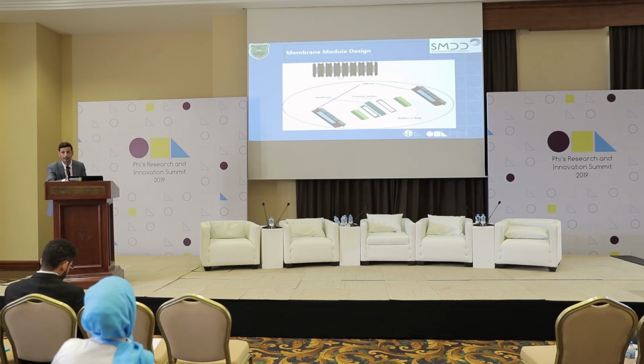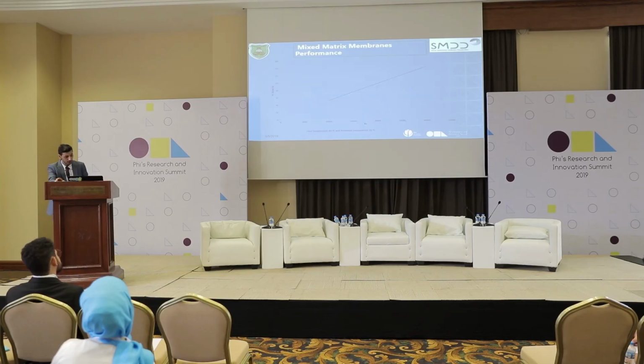We sent the membranes for testing to a Dutch company, because when you register a patent, you need what we call a third-party approval. Somebody that is completely an outsider, but is in the field, to test your membrane and prove that your claims in your patent are correct. And this company, Qtaishat, in the Netherlands, did this for us, and they were very happy with the performance, and they made the first order of the membrane from our company. Now, from a performance point of view, I've reached a flux of up to 140 liters per square meter per hour, which is 4 times higher than the reverse osmosis membrane.